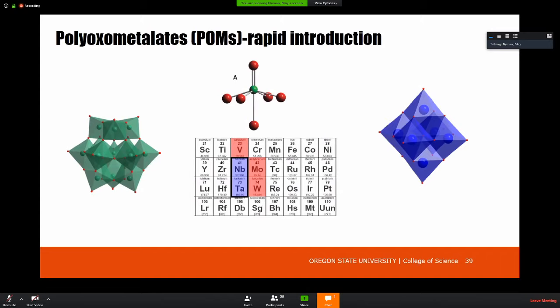With this hypothesis in mind, we checked by electrospray mass spec, and indeed we found this niobium-3 cationic fragment that is sheared off that decaniobate, and this is the other part of the solution. The small part that we are not seeing by X-ray scattering and so on. Okay, so we successfully published this in JACS, and the theme of this study is we are promoting chemistry with alkalis only, not with pH. Okay, so this is a very unusual mechanism to drive chemistry in water and with polyoxometalate chemistry more specifically.